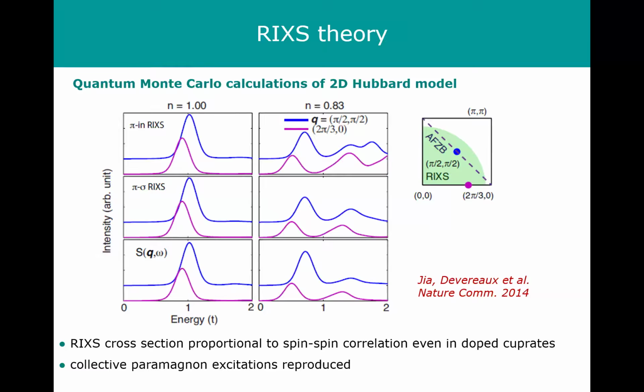So there were two competing views of what happens in resonant inelastic X-ray scattering. One was propagated here by Devereaux and others, who concluded from their Monte Carlo calculations of the Hubbard model that the RIXS process really visualizes the spin-spin correlation function, analogous to inelastic neutron scattering.